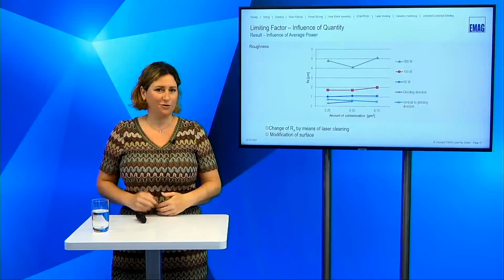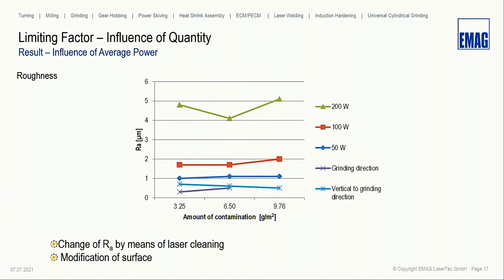But take into account not only this cleanliness, also the roughness, because you don't want to hurt the surface that much. We check also the Ra value, so with higher power for sure you get a higher roughness, and with decreasing power, you have a lower roughness. You saw at the beginning slide that you have a clean surface for all, but to have a good surface, you use, in this case, lower or average power. And the influence of laser cleaning, the limits of laser cleaning, or what can be laser cleaned, is now explained by Dr. Motz a little bit more in detail.